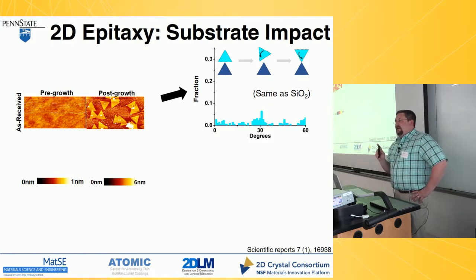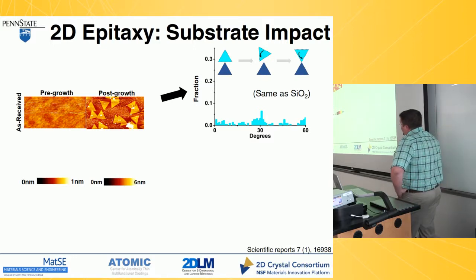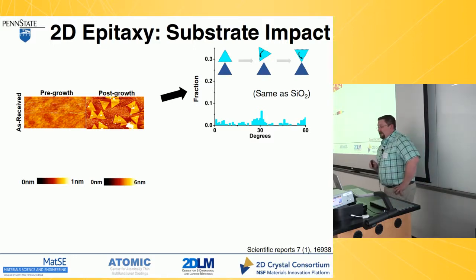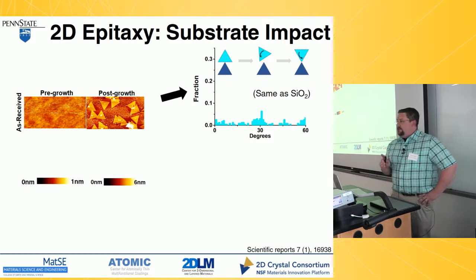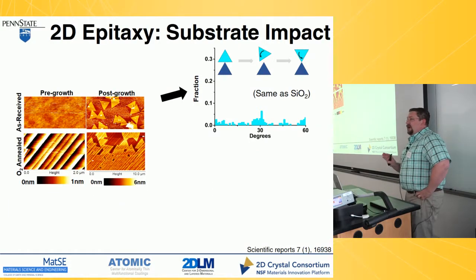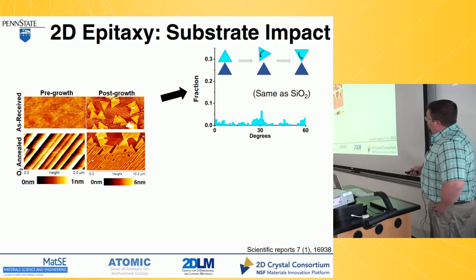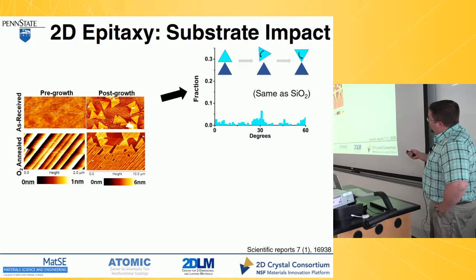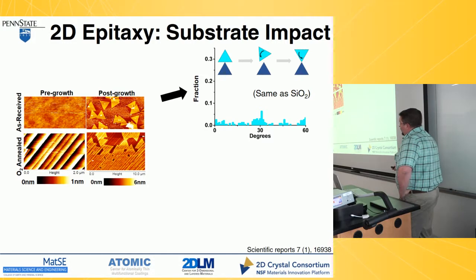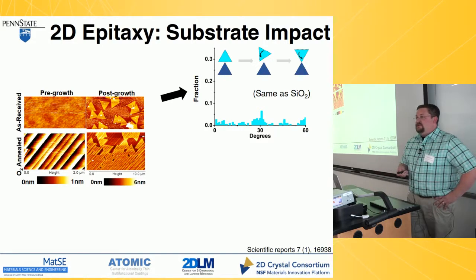So then we look back at some of the papers from the 70s, 80s, 90s, all of which were probably older than half the people in here, and said, okay, well, why don't we just anneal these things in oxygen or hydrogen? Because that's a pretty traditional thing to do with sapphire substrates. And when we did that, this is a little bit higher roughness than everything we have, but it shows a point that you can get this nice terracing on the substrate surface, right?